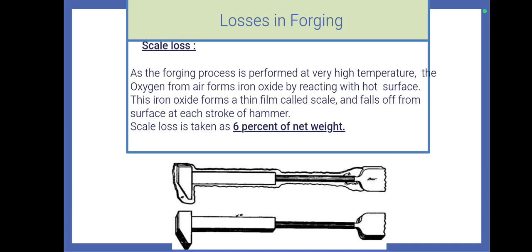When hammering is done, the scale is broken and falls down as waste. This material waste is known as scale loss. Generally, the scale loss is taken as around 6% of net weight.